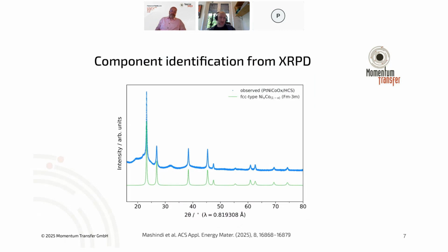So this is an example of just some kind of metal and metal oxide nanoparticles. So it's not interesting from a mineral perspective, but I wanted to demonstrate the fact that we can identify crystalline peaks, which show up as sharp peaks in your pattern. But in some cases, when you have sufficient information or you know what you're looking for, you can also find disordered or nanoparticulate phases. And so you can also discern these signals. You can see in this case, the peaks are much broader in the blue curve than in the green. And this is because the crystallite sizes are very much smaller than in the green curve.